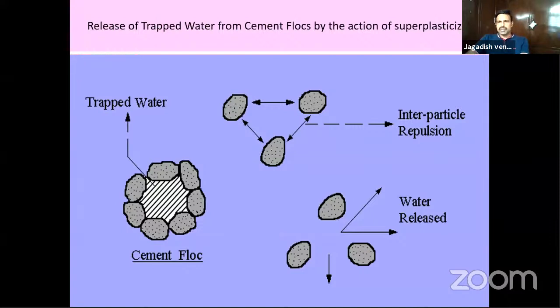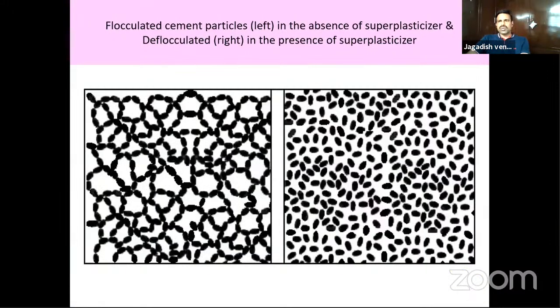There are different mechanisms we talk about depending upon the chemical admixture. So here, one such mechanism is interparticle repulsion. It creates different charges on the particles, and the cement particles get separated by adding the chemical admixture, and the water trapped inside these flocs gets released. That's how more water is available for the workability. You can see the difference between the flocculated and deflocculated cement particles after adding superplasticizer. This is a microscopic picture you can see.